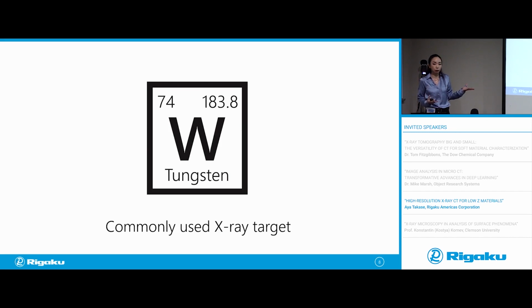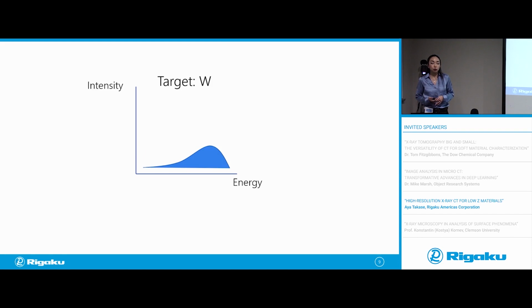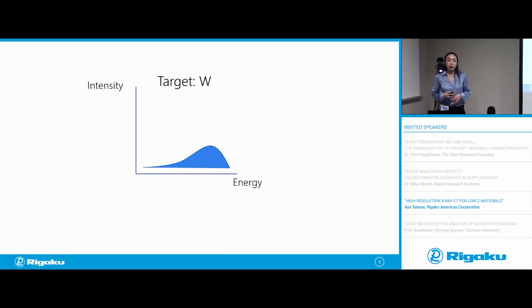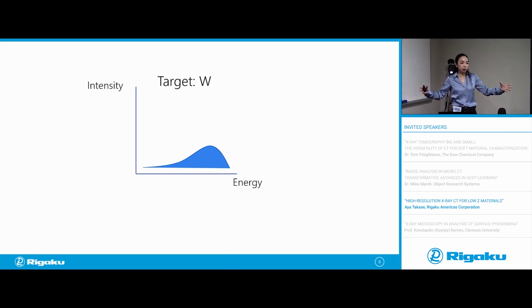So it's a really good target to use. And when you use a tungsten target, your energy distribution looks like this. You have energy as your x-axis and X-ray intensity as your y-axis. It's in general a kind of broad peak, and that peak position depends on the voltage you're applying between the filament and the target. The good thing about this tungsten target generator is you can apply very high voltage, 200 or sometimes even 400 kilovolts, to generate really high energy X-rays. You can shift that peak to the higher side by increasing the applied voltage.